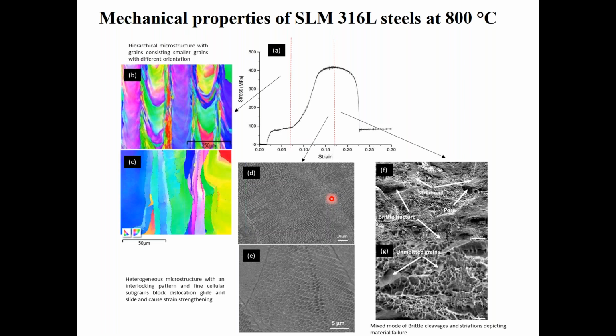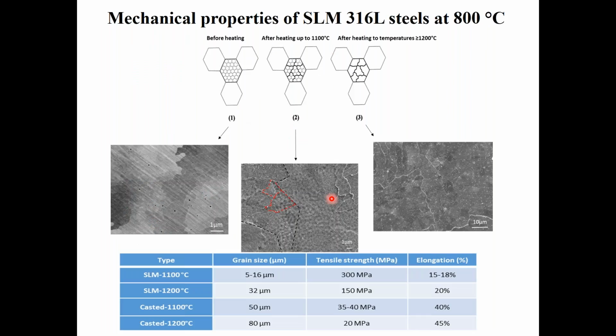Then we started thinking, how stable is this microstructure? First, this hierarchical microstructure is developed, the subgrains are formed, due to the segregation of certain alloying elements at the grain boundaries. So they make cells. And to break down those cells, we need to diffuse those alloying elements from the grain boundaries or subgrain boundaries. So we started heat treating them at different temperatures for different times, trying to understand why and how long this microstructure is stable. We heat treated at 1100 degrees centigrade and 1200 degrees centigrade and investigated the mechanical properties as well.